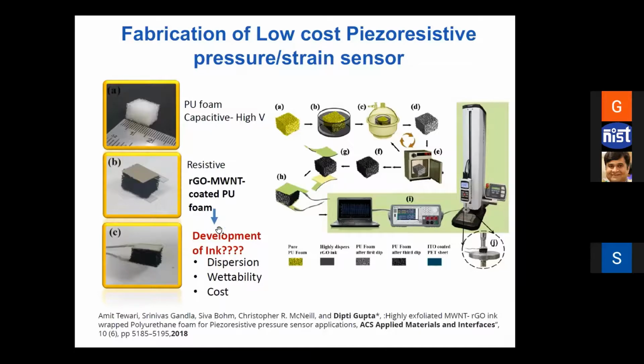So what we did, we created a coating, right, based on reduced graphene oxide and multi-walled nanotube, so that it covers the exoskeleton of this polyurethane foam, and it becomes a piezoresistive device. But development of the ink itself took us lots of time, because what we wanted was very good dispersion, wettability, and ultimately low cost, right? So we also worked on the ink part of it, and this is a quick picture showing how the devices are fabricated and tested, right?